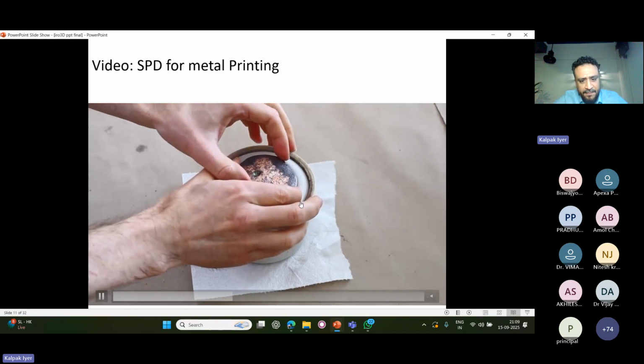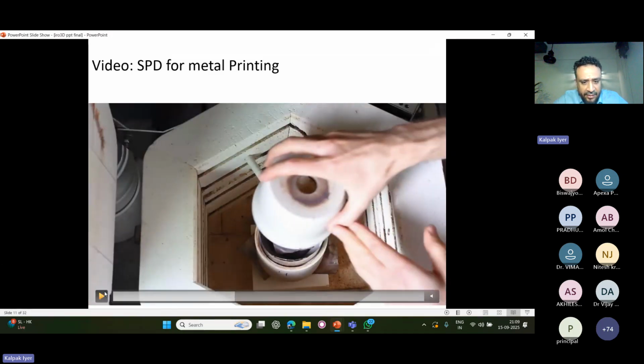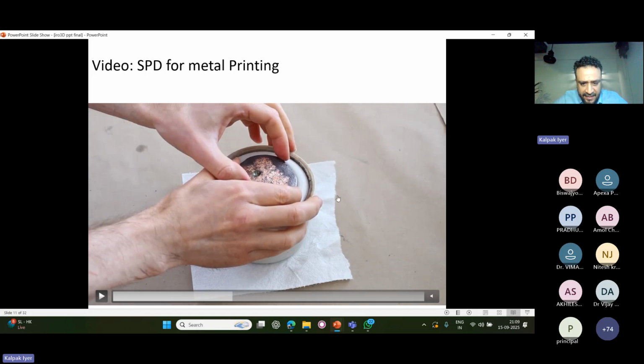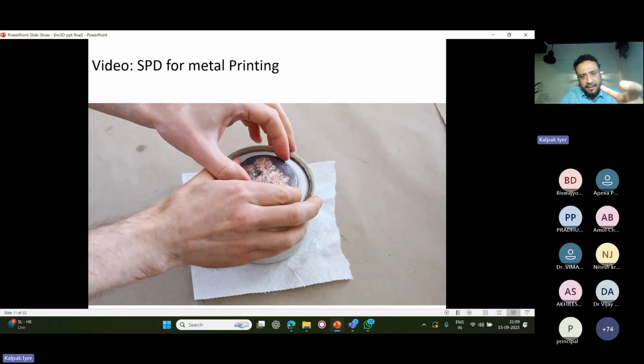That runner was of the iron powder. On top of that, you can see all the white around it was the sand. This is silica sand, very neatly deposited. On top of the runner, we place an infill metal. The infill metal is the alloying metal, the metal that is going to melt and alloy into the iron powder. Here, as you know, the iron powder is the build powder, and we are using copper as the infill. So we are expecting the end alloy to be an iron copper alloy.